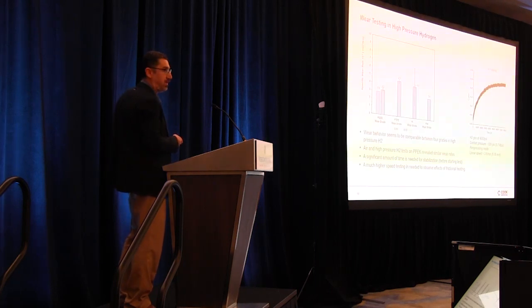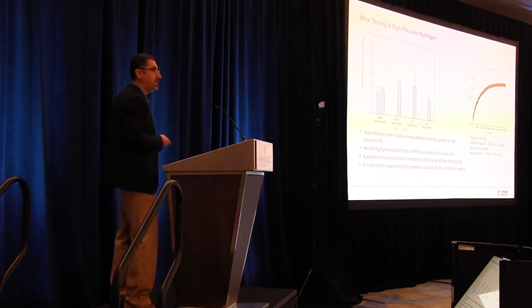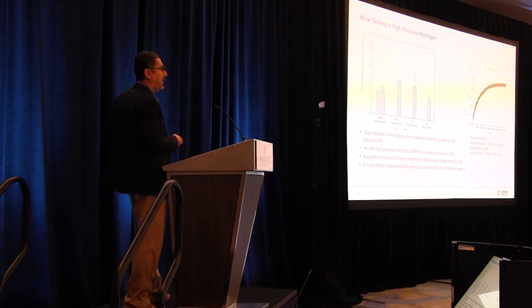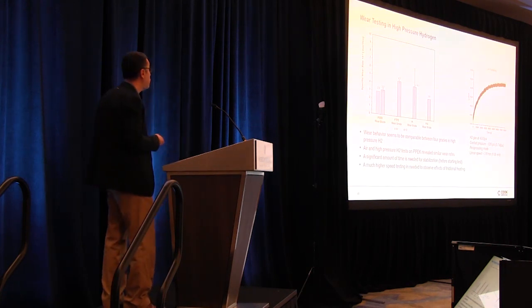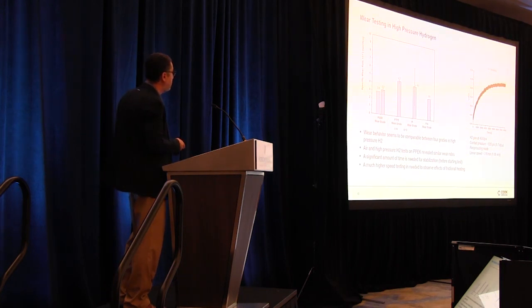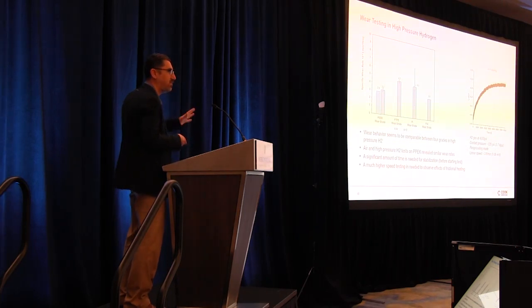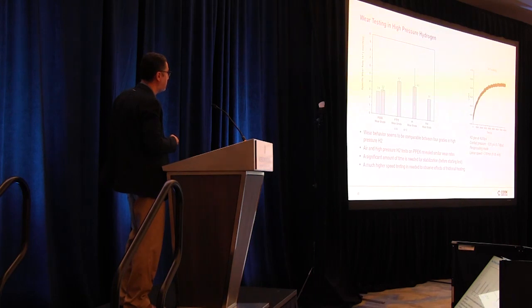Now some data coming from our wear testing. So this is coming from a very specialized test equipment. We actually put our tribometer in a pressure vessel. We put in high pressure hydrogen, pressurize the gas to 4,000 psi, and we run the wear testing in reciprocating mode. And we get the wear rates for 4 different materials again. So in terms of wear rates, you see some of the numbers are higher and some are lower, but these we consider falling into the same order of magnitude, and we consider all of these materials have a similar wear rate in high pressure hydrogen. And we also have a little bit of data coming from the air at the same exact conditions for PEEK, so we are also seeing a similar level.